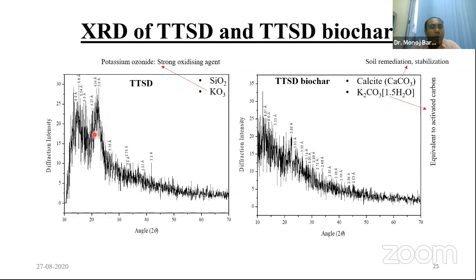Also, from the peaks obtained at certain diffraction angles, which are ultimately converted into d-spacing values in angstroms, some inorganic compounds can be identified. For example, based on peaks at different diffraction angles, silica, that is SiO2, and potassium ozonide, KO3, can be identified as present in this kind of biomass. As we know, potassium ozonide is a very strong oxidizing agent.